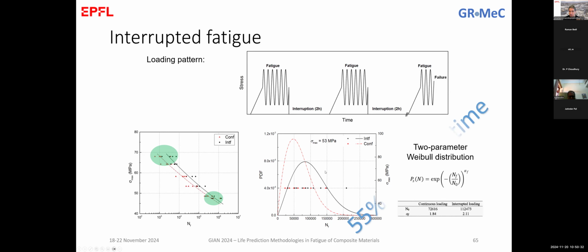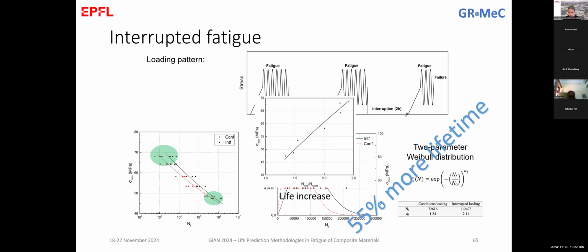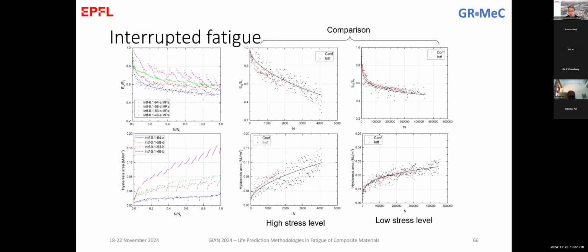And of course, as we said before, it becomes more significant when we analyze statistically, when we go to 95% reliability, for example. This increase is significantly more. But at least we see that we have 55% more lifetime, talking in a deterministic analysis. We have 55% more lifetime when we interrupt the fatigue testing. So again, discussing the stiffness degradation, we see this recovery of stiffness, and we go down, and then we recover, and then we go down again, we recover, and we go down again. And this more or less justifies this extension of lifetime.